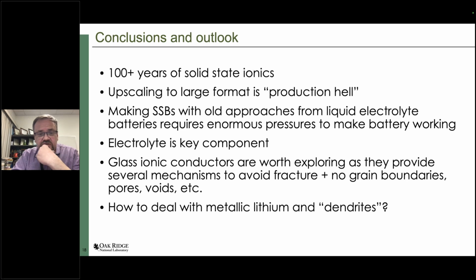Electrolyte is absolutely the key component here, which connects two electrodes, and there are quite unique requirements on its mechanical behavior. It needs to be sufficiently hard to work with lithium, but at the same time, it needs to be resistant to fracture. And we think, based on our experience, and not only ours, that glass ionic conductors are really worth exploring because they provide several mechanisms to avoid fracture. Plus, they don't have any grain boundaries, so the residual electronic conductivity is pretty much zero in these materials. And the question of how to deal with metallic lithium and what we call dendrites, even though not all of us like this term, my colleague Eric Herbert, the next presenter, will explain in great detail.